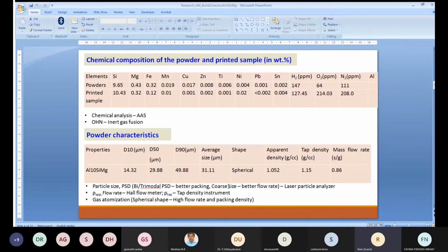Now let's get into our research. This is the chemical composition of the powders and printed samples. We have measured the chemical composition through atomic absorption spectroscopy, and X-ray fluorescence also can be used. Inductively coupled plasma optical emission spectroscopy can also be used to measure the chemistry. For gaseous elements like hydrogen, nitrogen, oxygen, there is a technique called inert gas fusion, which can be used to measure oxygen, hydrogen, nitrogen.